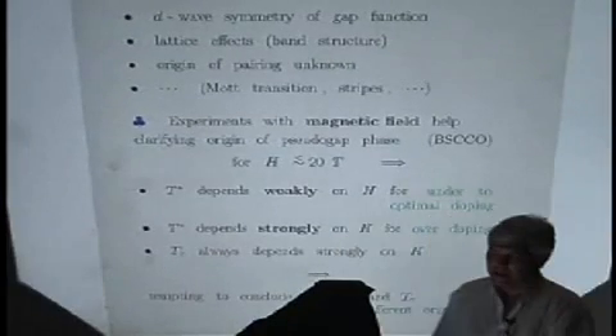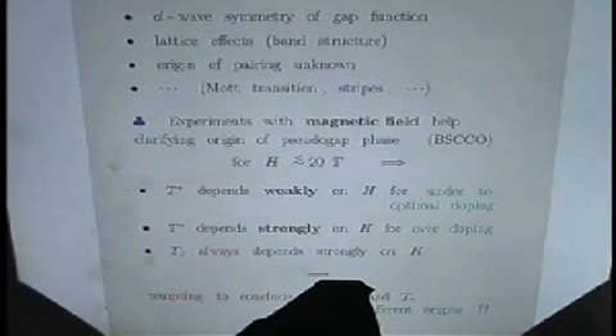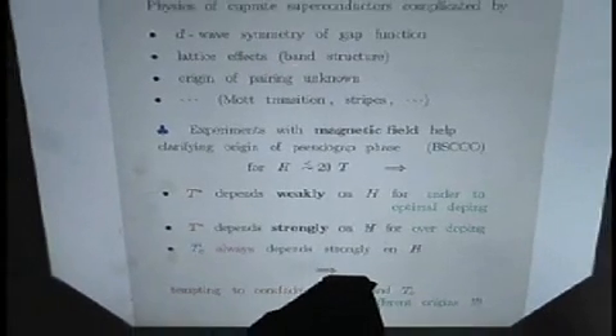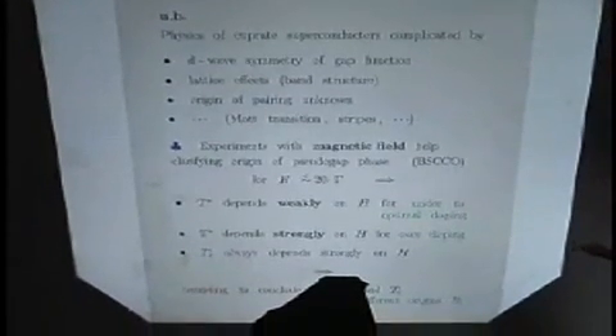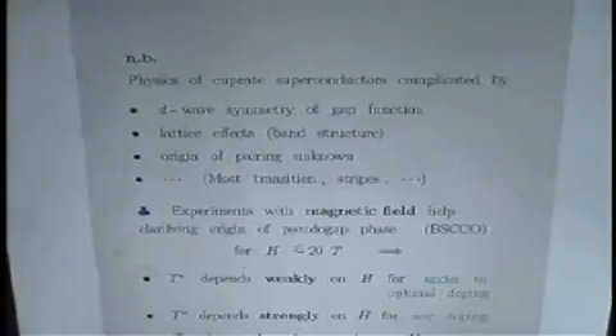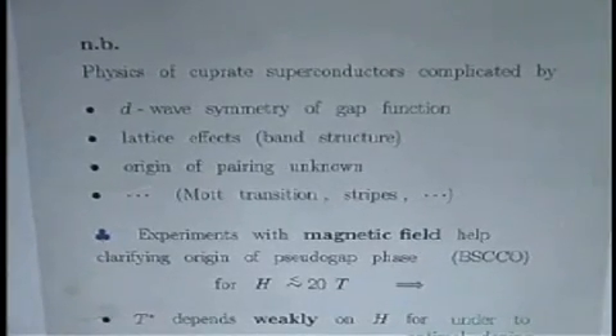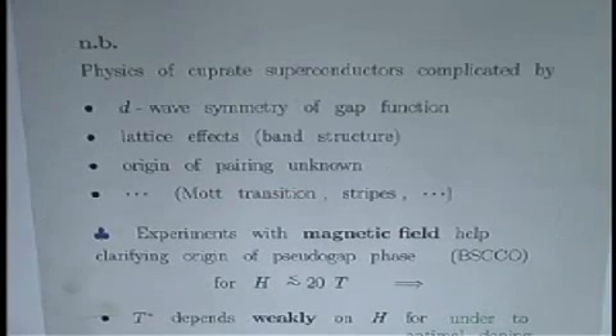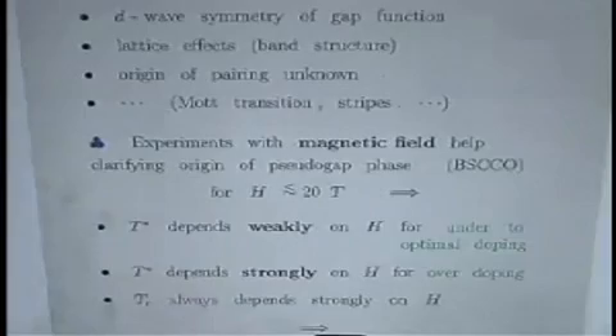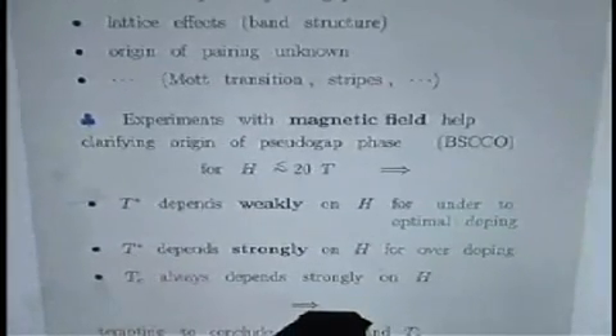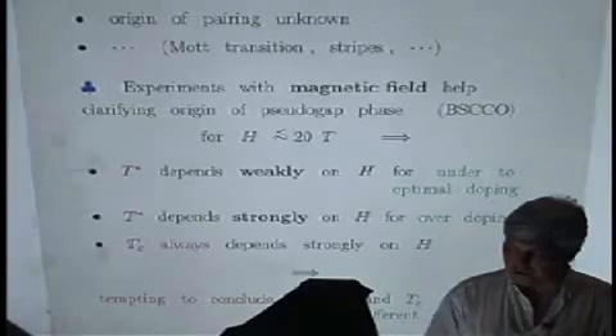Unfortunately, the physics of the pseudo-gap is complicated by several features. The number of degrees of freedom is very large. First of all, the gap parameter has D-wave symmetry, it's not S-wave symmetry. You get lattice effects, like the band structure, which represents a van Hove singularity in the density of states and so forth. The origin of pairing is unknown, but is not of concern to us. And then you get additional effects, like the Mott transition, a localization transition in the low doping region. You get antiferromagnetism organized in stripes, and charge also organized in stripes. So you get really a lot of degrees of freedom which can obscure the physics which is behind.